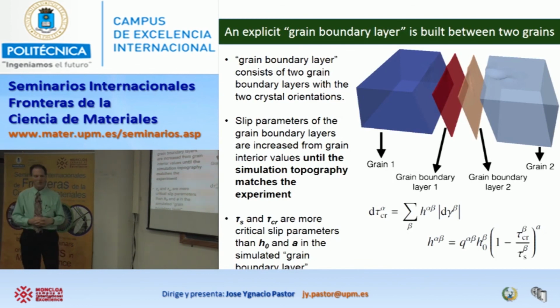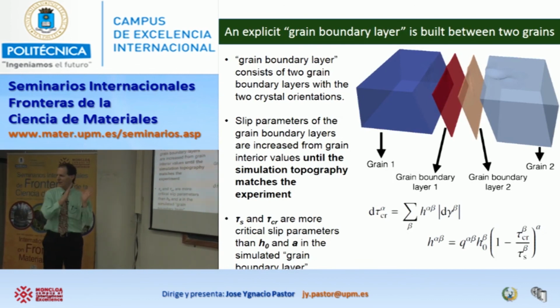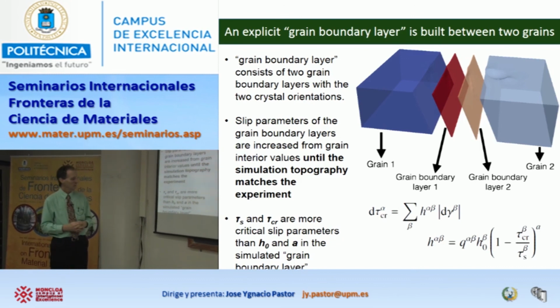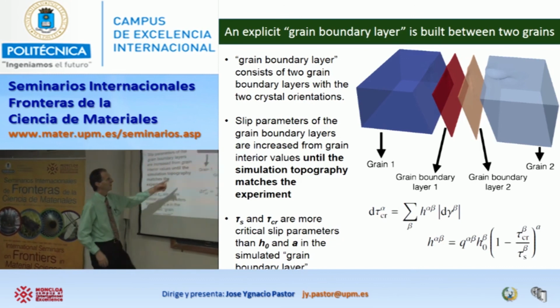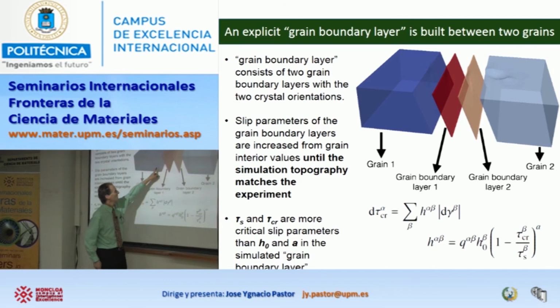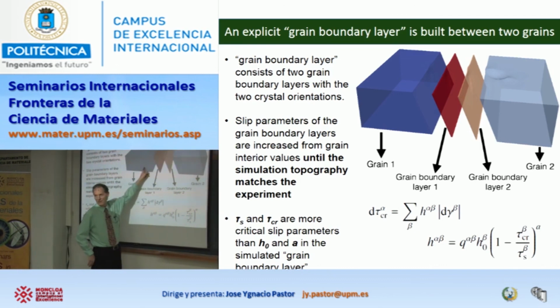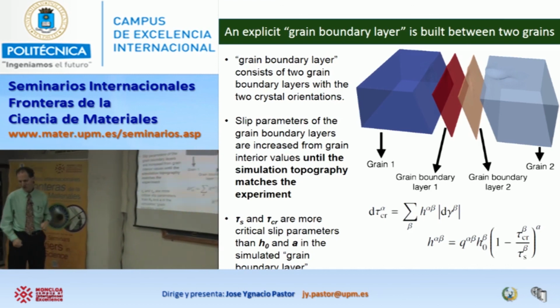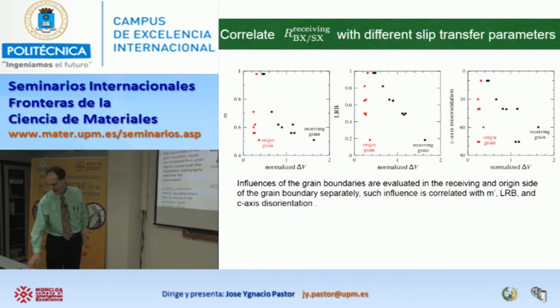So then we ask, well, can we simulate what's happening at the grain boundary by creating a layer of elements on either side that's harder than the parent grain on either side? It's not perfect, but maybe I can somehow increase the hardness. And so computationally, we can play that game.